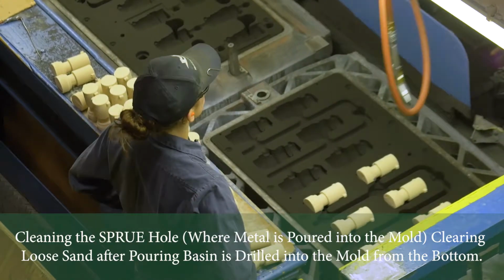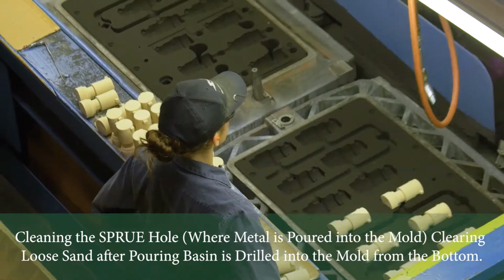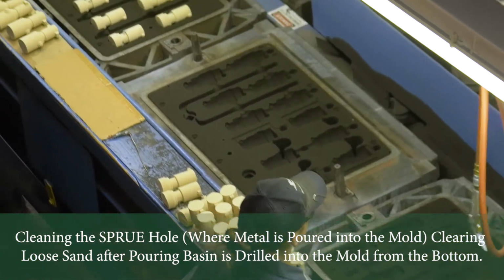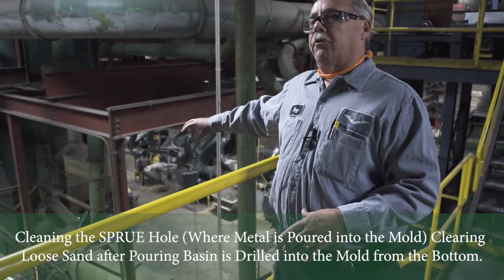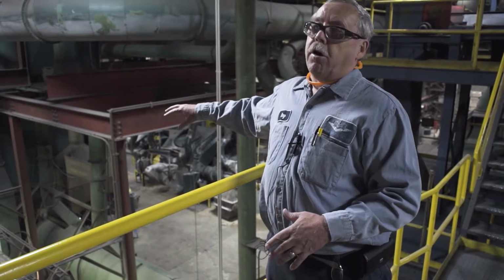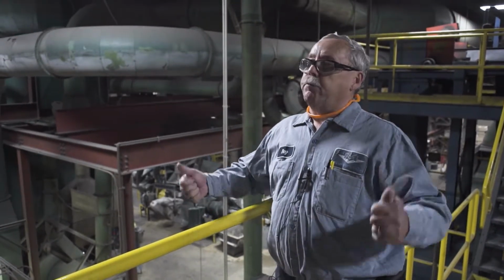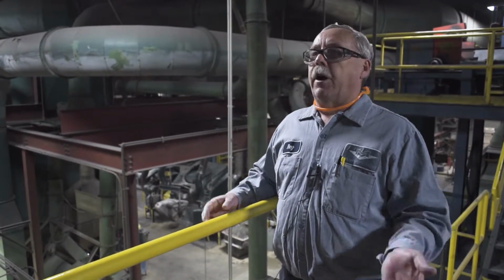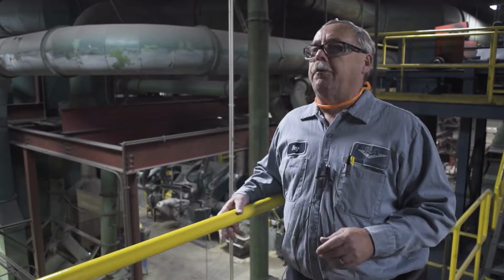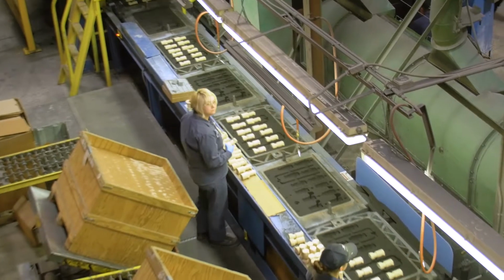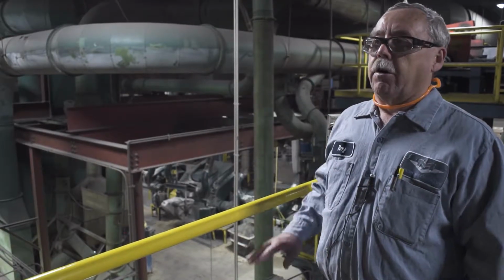After that, every other mold gets a core set in it. That's the bottom half of the mold, the drag, and the top half of the mold is the cope. We have pins and bushings that do the alignment from one half to the other half, so we get good alignment of the casting. Out at the end, and we'll show that later, we put the two halves together.